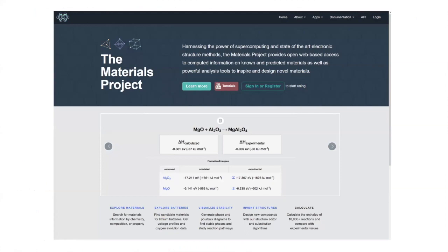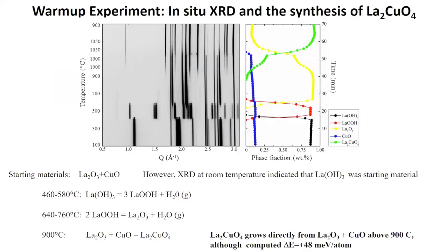So of course, at this point, one is a little discouraged and wonders if it's possible to make touch again with the basic idea, which is that the electronic structure calculations could give us some guidance. And for that, we turned to the Materials Project as a source of DFT calculations. And so in this next step of this talk, I'm just going to go through those syntheses and show you how the total energy that's associated with each one of the reactions actually develops. So here again is the synthesis of lanthanum cuprate, and this is the reaction. Lanthanum oxide plus copper oxide gives us lanthanum cuprate.